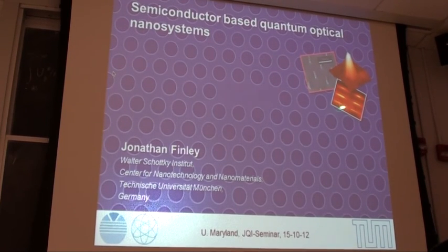Now, why are we doing this? Why are we exploring this type of different semiconductor nanostructure? Well, many of you working in the field will know that in zero-dimensional nanostructures, many of the quantum degrees of freedom that you can interact with, things like, for example, the spin of an electron or the spin of an exciton in the system, actually are very robust quantities compared to higher dimensional systems like quantum wells. So this, if you like, is an archetypal quantum memory. Embedding it in some kind of photonic system allows you to interact with it.